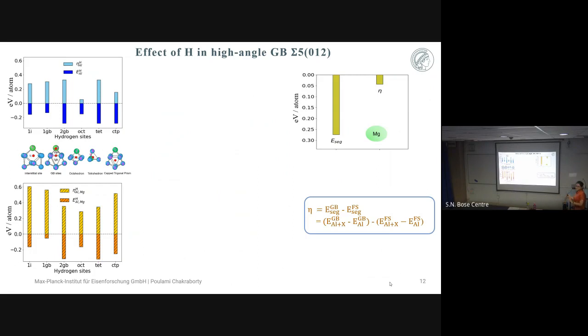So the free surface is what you get when the grain boundary is formed, and there is another case I have shown where the hydrogen is present and the solute element is present, and a crack is formed. That is the free surface. In this case, as you can see, the strengthening energy is the thermodynamic driving force. It shows whether the presence of this particular solute element or these defects will lead the system to be happy at the grain boundary, or whether it will be happy to form a free surface.